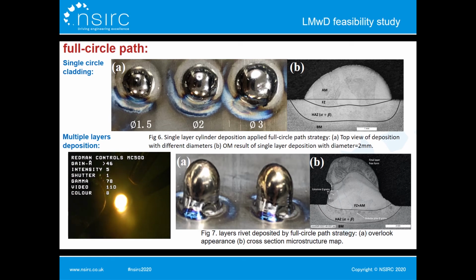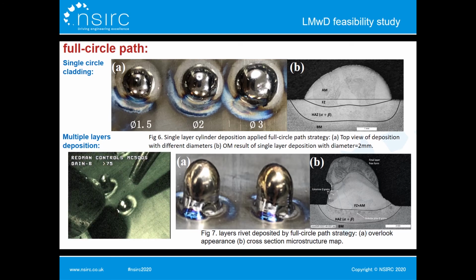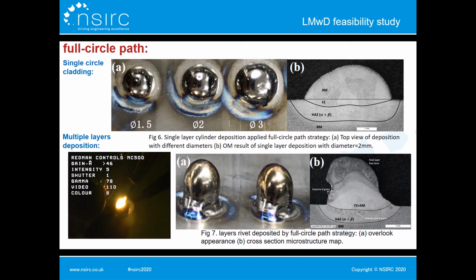And look at the interface between the added material and the substrate. They have joined quite well in the microstructure maps. Therefore, although both the single-circle and full-circle strategies can successfully build up the cylinder deposition, after the results analysis and comparison, we can easily conclude that the deposition applied by the full-circle path strategy can achieve a better result, both in the geometrical and macrostructural aspects.